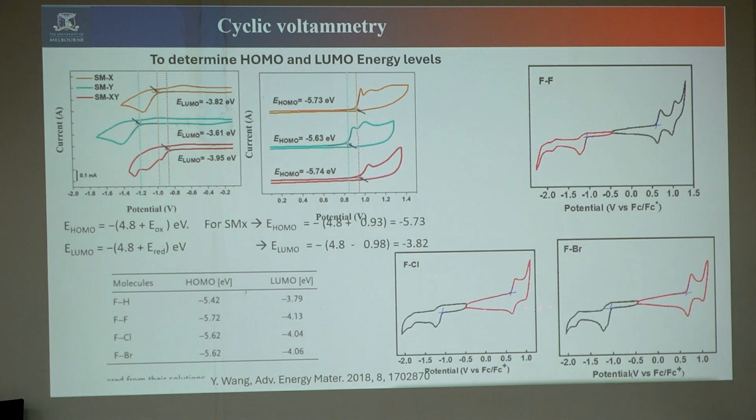You follow the same thing for the absorption spectrum also. This is the correct way of getting the answer to calculate the HOMO level. I drew one line here, the baseline, and this tangent where the oxidation starts. The meeting point is what you take as the onset. I hope that is clear.